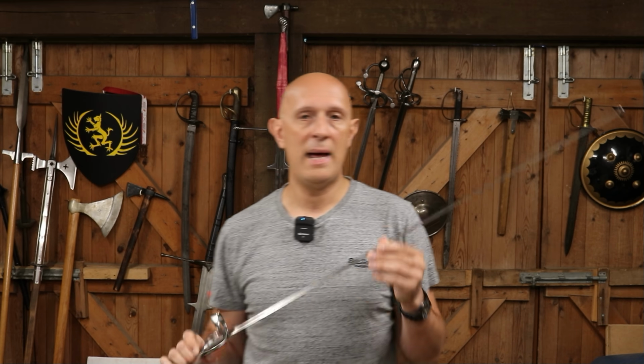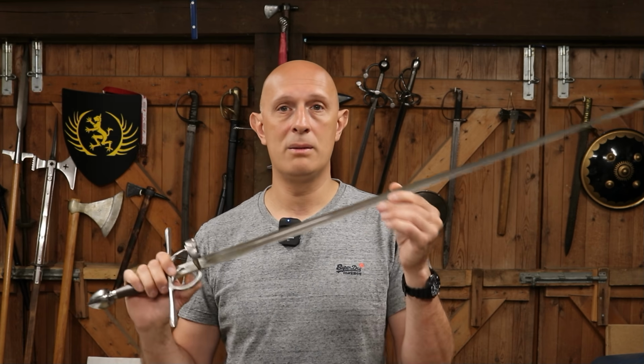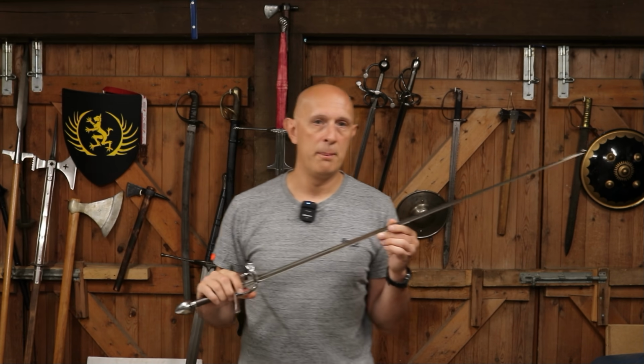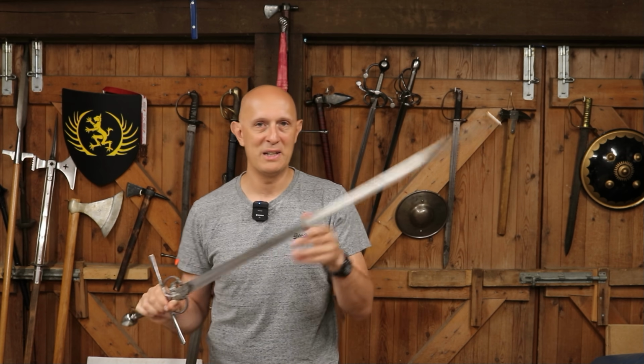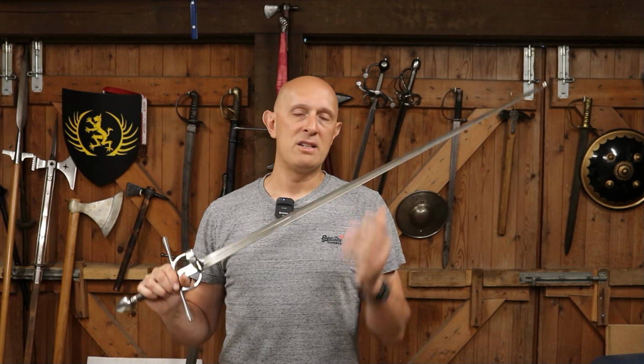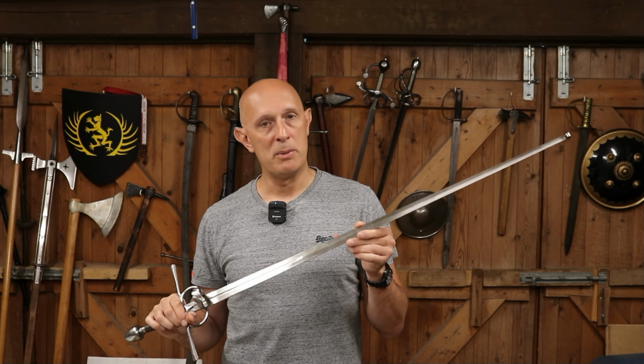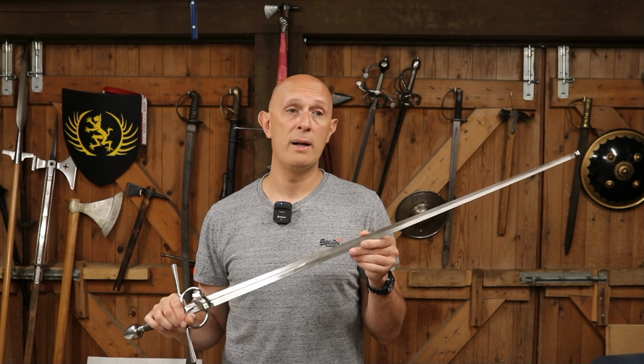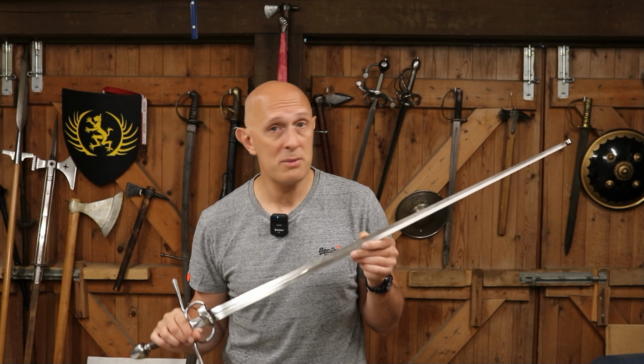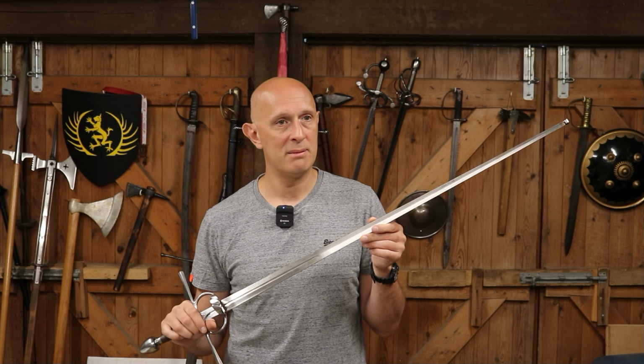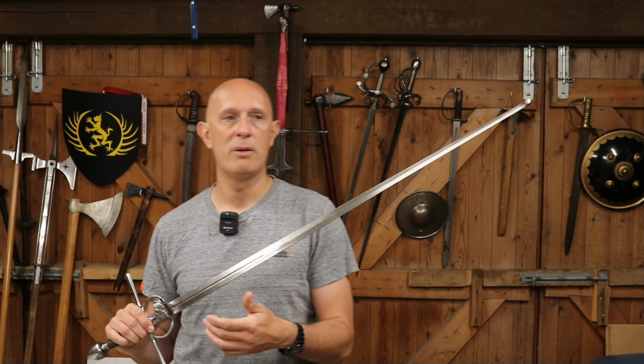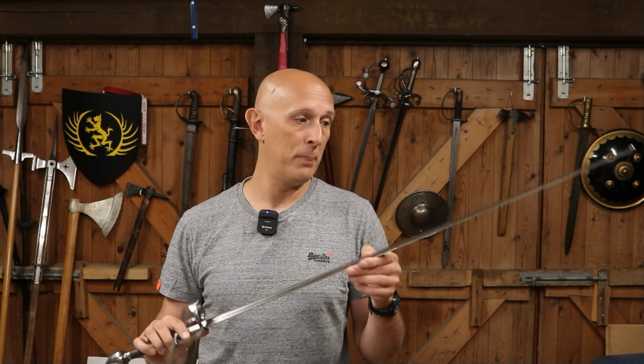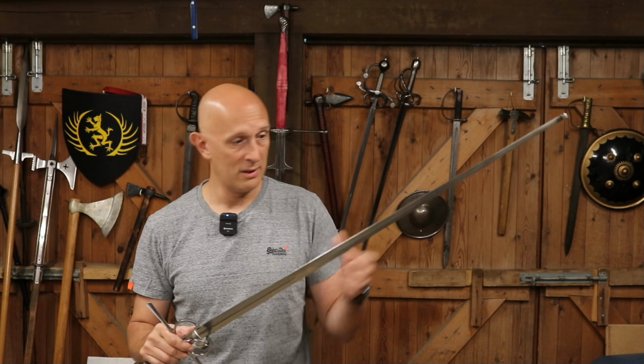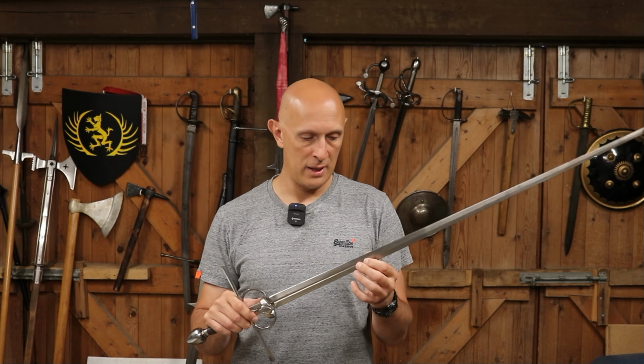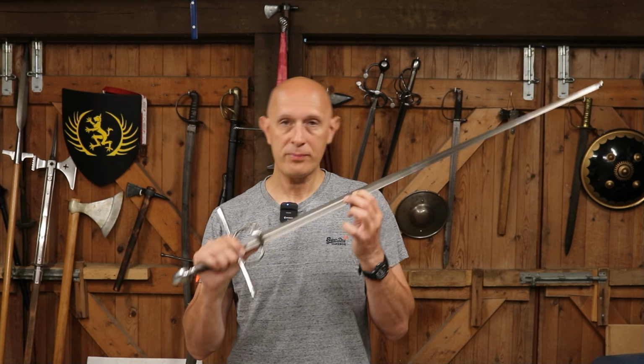However, according to the tested medieval and Renaissance swords that we've seen, and obviously we're talking about 1,000 years of period there from 500 to 1500-ish, it does seem that most European swords varied between 25 and 45 Rockwell. And sometimes high status swords weren't necessarily the harder blades. There was a degree of randomness thrown in because of the nature of the materials that they were using and the inconsistency and inclusions like slag in the earlier blades.